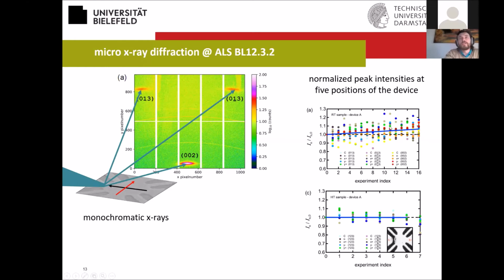What we find here is that on the one hand, our signal to noise ratio is pretty bad. On the other hand, we see that there is a general trend for the intensity of our X-ray peaks to increase as we go through this experiment and pulse and pulse and pulse. So generally, the intensity coming from these spots increases. In contrast, our high temperature epitaxial device doesn't do that. Here, the intensity is essentially flat.